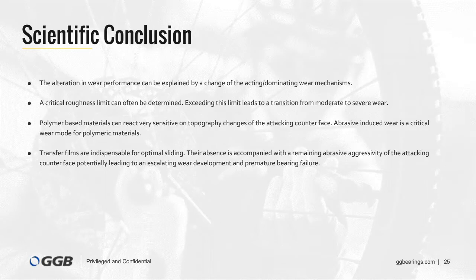So now I come to the scientific conclusion of this talk. A change in wear performance can often be explained by a change of the acting dominating wear mechanism in the contact. We found out that polymer-based materials can react very sensitively to a topography change of the attacking counterface. Abrasive wear actions are seen as a critical wear mode for polymeric materials. We also have seen that transfer films are important for optimal sliding because they protect the bearing surface from aggressive wear actions of the counterface.